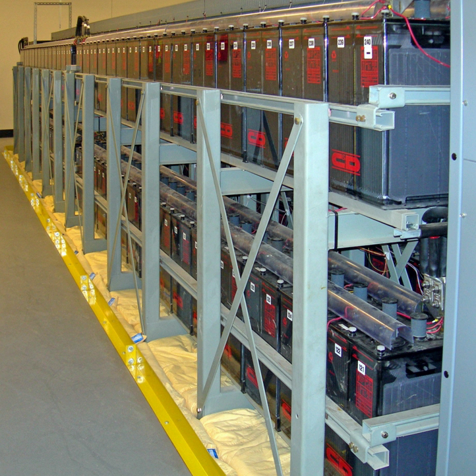For some types, the maximum charging rate will be limited by the speed at which active material can diffuse through a liquid electrolyte. High charging rates may produce excess gas in a battery, or may result in damaging side reactions that permanently lower the battery capacity. Very roughly, and with many exceptions and details, restoring a battery's full capacity in 1 hour or less is considered fast charging. A battery charger system will include more complex control circuit and charging strategies for fast charging than for a charger designed for slower recharging.